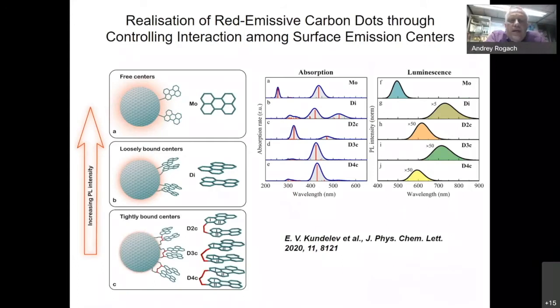And another way to realize red emissive carbon dots will be to rely on surface ligands, on attached moieties. Still they are nitrogen doped here. And this emission center, if they interact stronger, so we can compare this so-called free center or loosely bound center, like what is shown here, or tightly bound center, what is shown here. When we move from situation A to B to C, we will move the emission to red wavelengths as well. And this has also been shown theoretically by my colleagues from ITMO University in Russia.